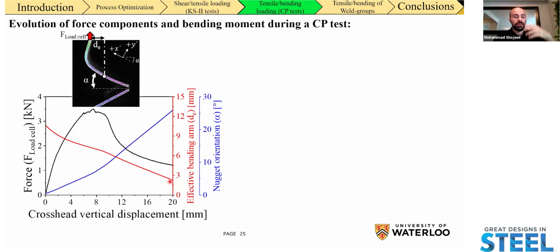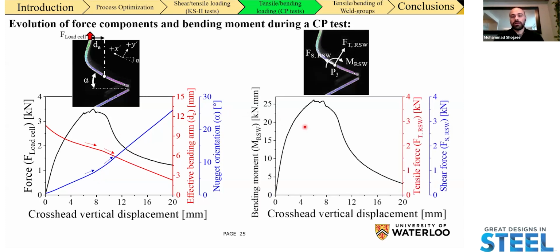At the same time, we have an increase in the orientation of the nugget. What is interesting is that as we cross the peak load frame, the rate at which the arm reduces and the nugget orients itself changes, because the sheet is detaching from one side and rotating at a faster pace. We can also plot the force components and the moments at the same time. The black shows the bending moment, the red shows the tensile force component, and we also have a negligible amount of shear force developing throughout this test. This test is not intended to develop shear force, so the magnitude of the shear force is really low.